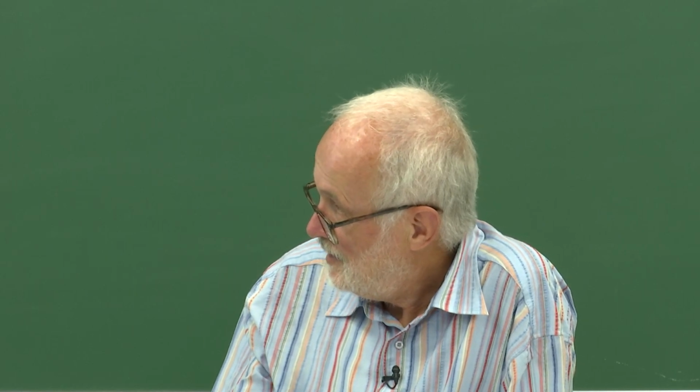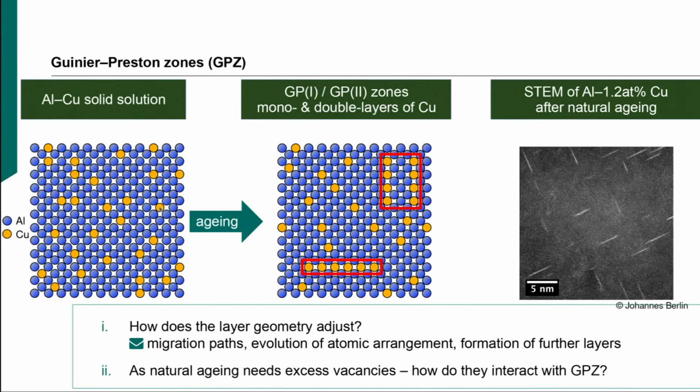Yeah, and applying these potentials, as we do in Monte Carlo, he started with a homogeneous alloy and then let it age for some time. And indeed, it formed nice Guinier-Preston zones. If you just consider nearest neighbor interaction, you would never get platelets.